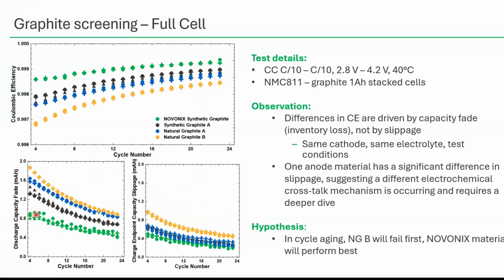But here, we're seeing this difference in coulombic efficiency is actually driven by the difference in the fade rates of the cells. This is due to losing lithium inventory into SEI growth or active material loss, because we're fixing what's happening at the cathode and changing what we're doing at the anode. So we're seeing a lot of these differences come up in fade, whereas for most of these materials, we see almost the exact same slippage. These electron donating reactions that typically originate at the cathode are the same in each of these cells.